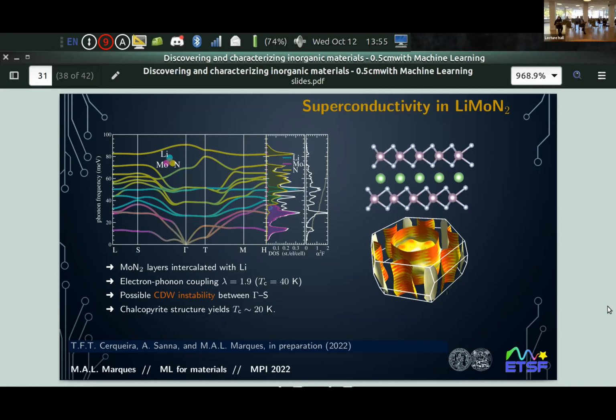We also tried the same composition in the chalcopyrite structure, that is the second, let's say, metastable structure. We get 20 Kelvin. Now, there's just one small problem. This dip here is related, we think, to a charge density wave instability. If we are on one side of the instability or the other one, it's very hard to know. We are certainly very close to charge density wave instability. That's the first problem. So obviously, if you have such instability, it will decrease the TC.